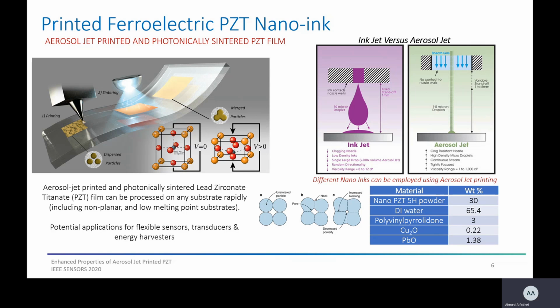If we look at the picture on the left-hand side, there's an illustration of the process that we've been conducting, starting with printing, going through sintering, and then ending up with the functional device. Aerosol jet printing technique was used to produce the PZT films. This technique is capable of depositing inks having a wide range of viscosities up to 1000 centipoise, enabling high-density PZT deposition. Aerosol jet is different from the well-known inkjet printing, which is more challenging when it comes to printing nanoparticle-based inks or high-viscosity inks.